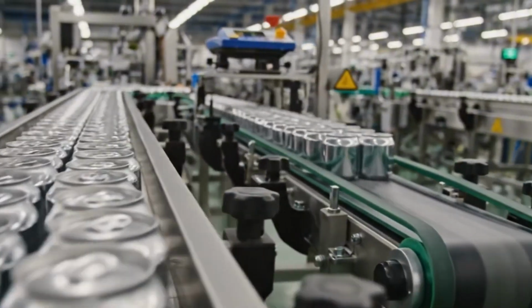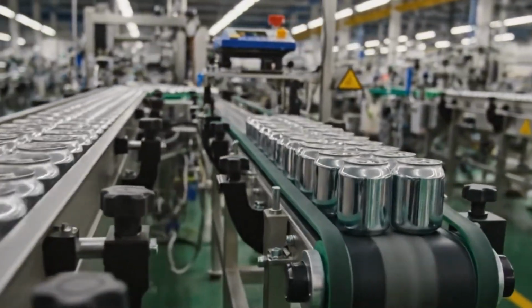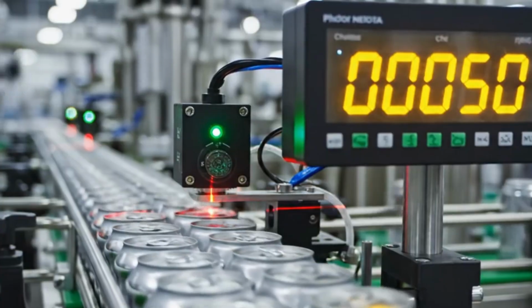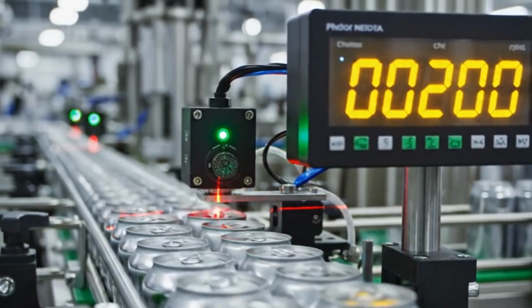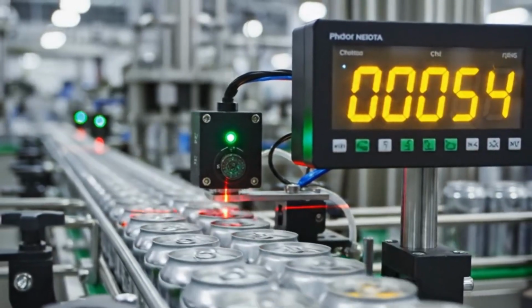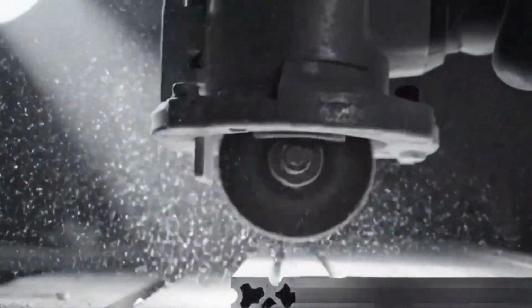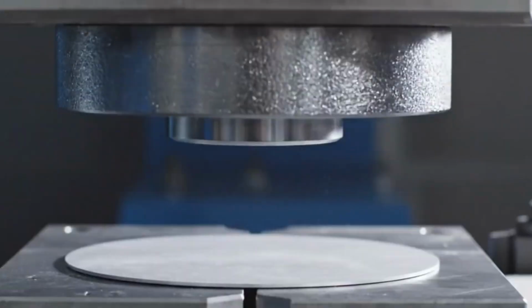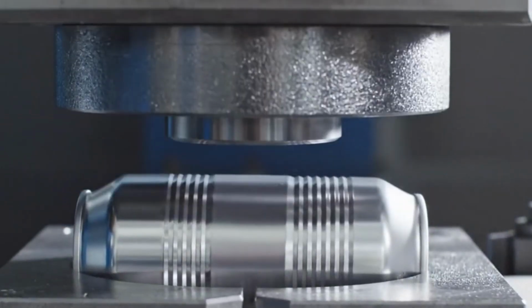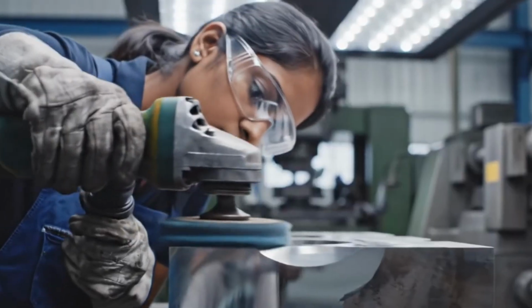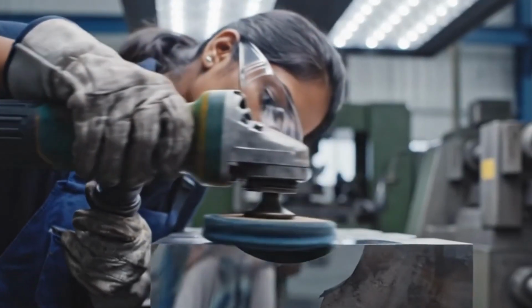If necking force rises by more than 5%, circumferential wrinkles form instantly, collapsing the can before the next die ever hits. Too little force and the step isn't clean, too much, and the wall buckles. The final neck shape determines which lid fits and whether the can survives carbonation pressure.